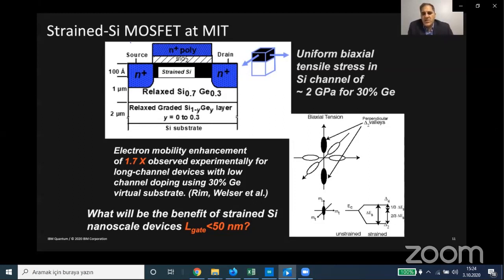And looking down here in this figure at the energy diagram, recall that the conduction band of silicon has 6 conduction band valleys that are degenerate. Due to the biaxial strain, in-plane strain, this degeneracy is split between the 4 levels that are in plane and the 2 out of plane.